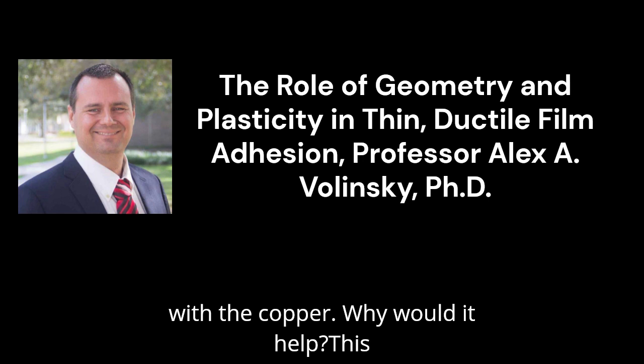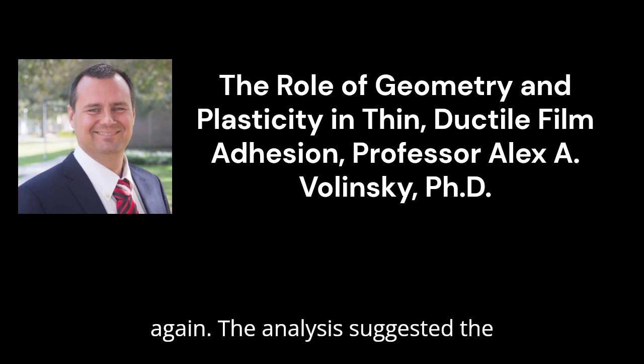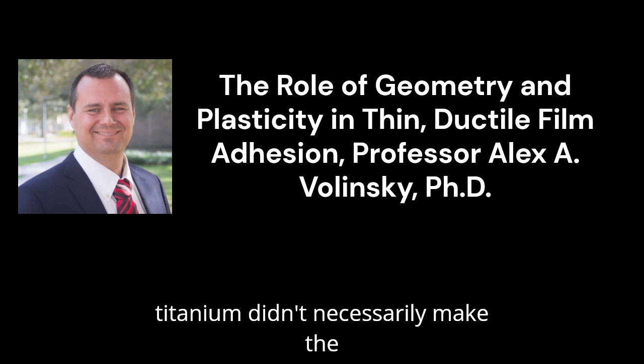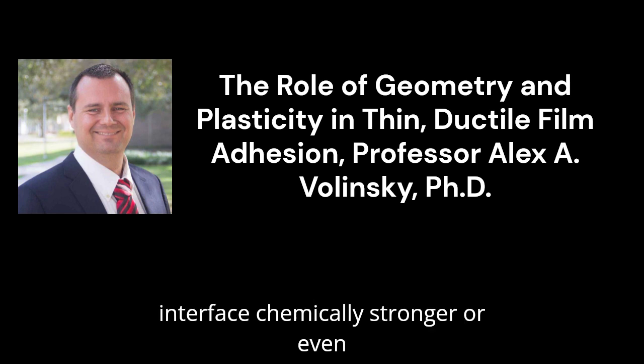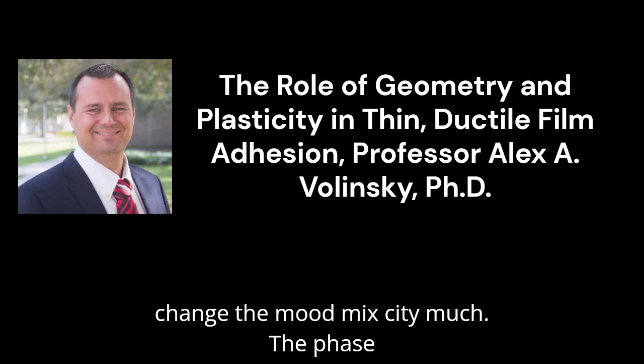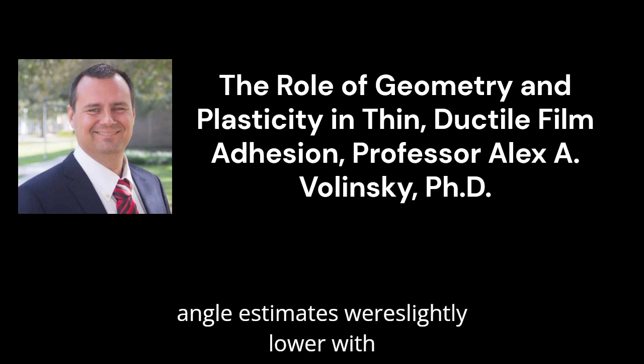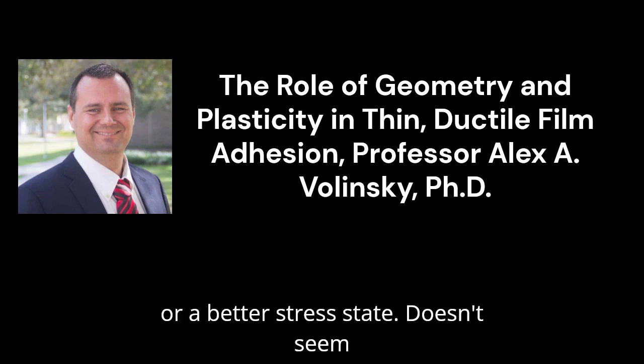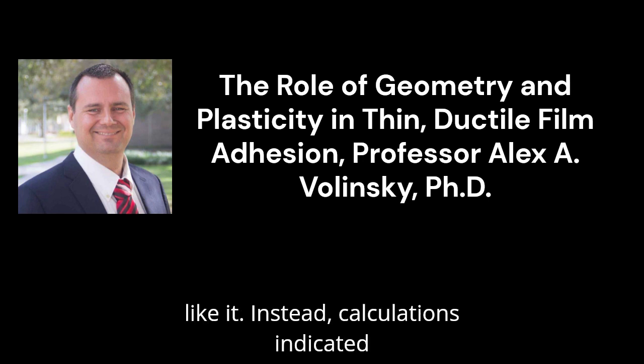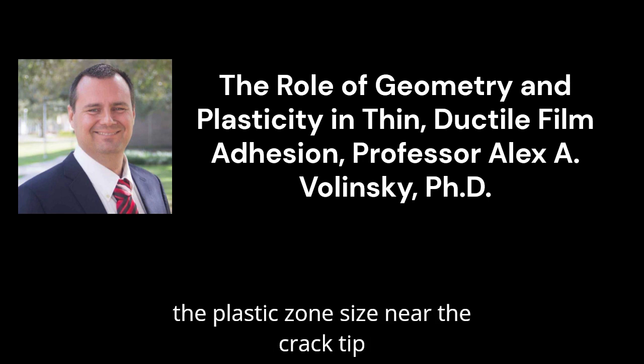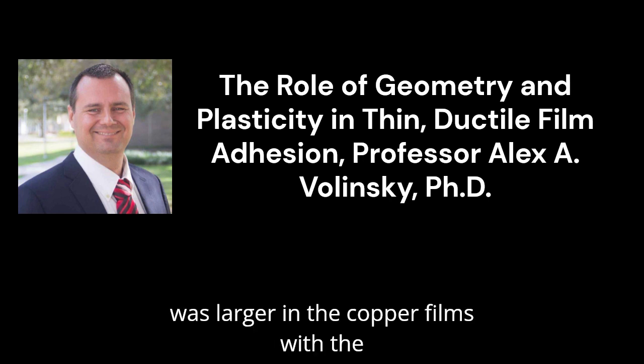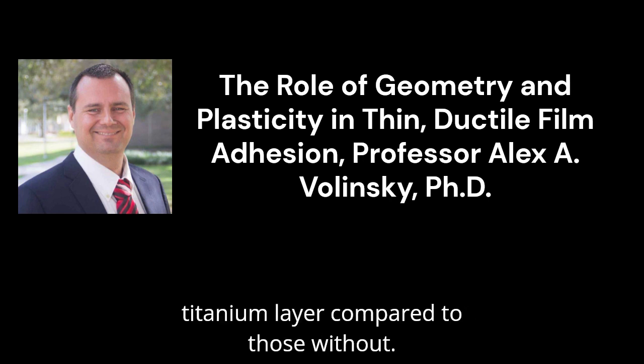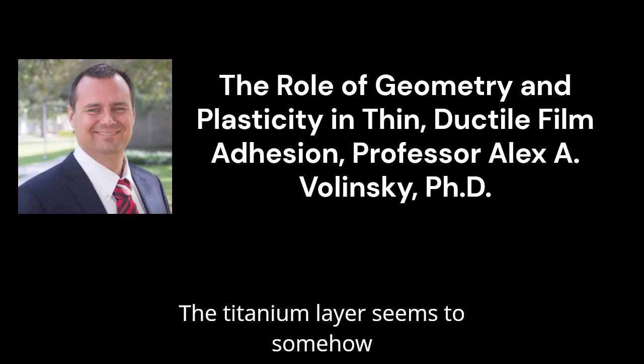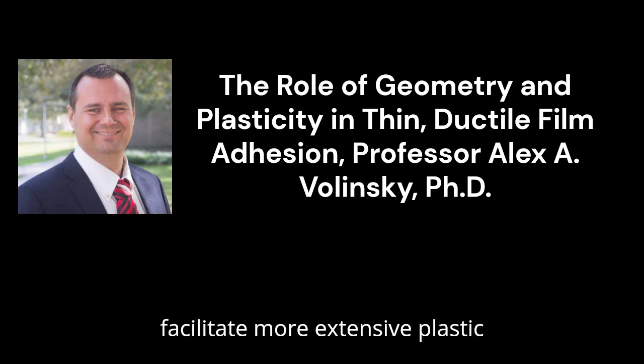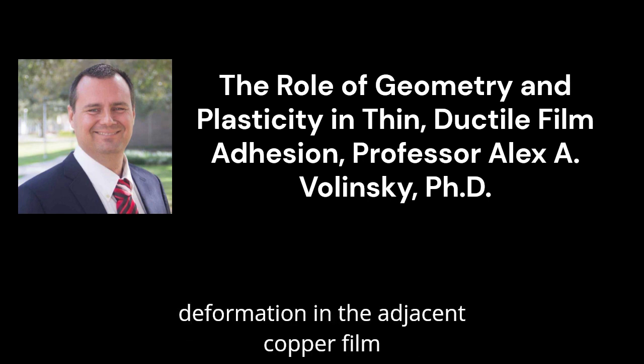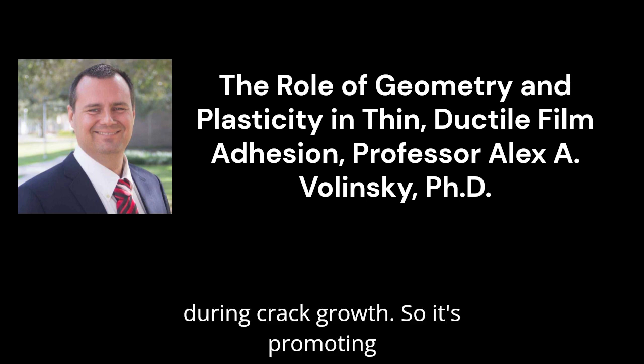Why would it help? This is where the plasticity insight is key again. The analysis suggested the titanium didn't necessarily make the interface chemically stronger or even change the mode mixity much. The phase angle estimates were slightly lower with the titanium. So it wasn't a better bond or a better stress state? Doesn't seem like it. Instead, calculations indicated the plastic zone size near the crack tip was larger in the copper films with the titanium layer compared to those without. The titanium layer seems to somehow facilitate more extensive plastic deformation in the adjacent copper film during crack growth.